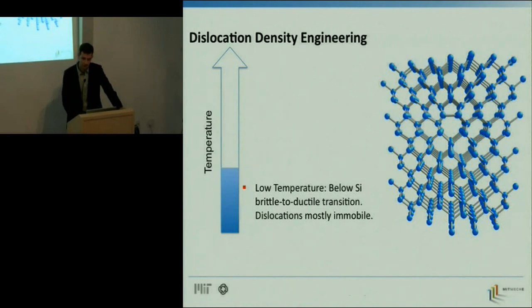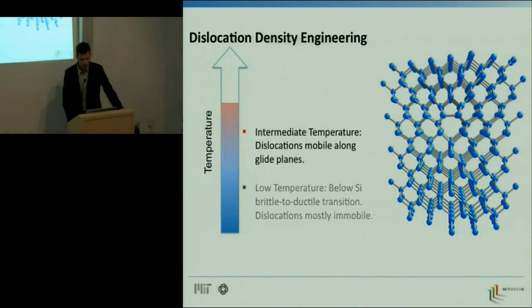We know that at low temperatures, dislocations really don't move anywhere. Silicon is a brittle material like glass. If you push it, it'll deform elastically, meaning just bonds will stretch but won't slip. And eventually, if you keep pushing, the thing will just shatter. And the same is true for silicon at room temperature. As you start increasing the temperature a bit, you can actually have the material deform, just like a paperclip would, a piece of metal, a ductile material. You've gone above the brittle-to-ductile transition temperature.